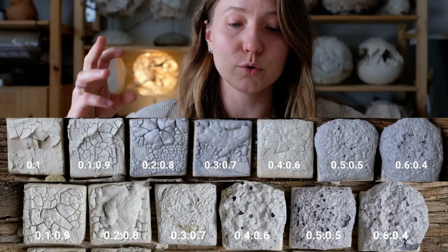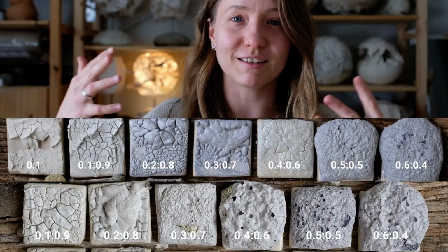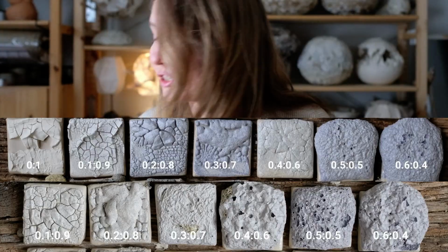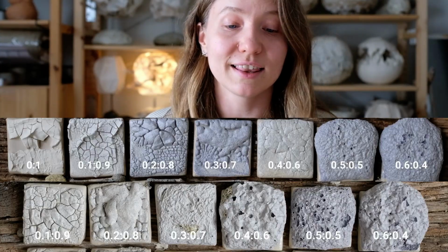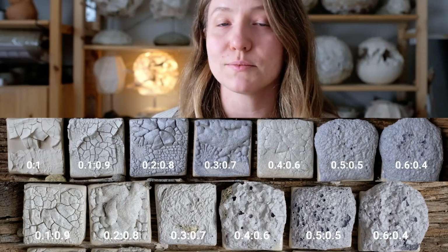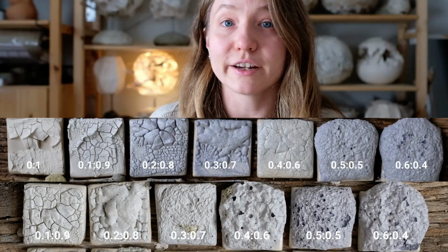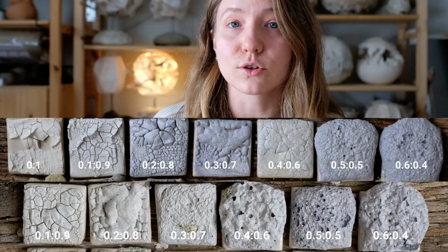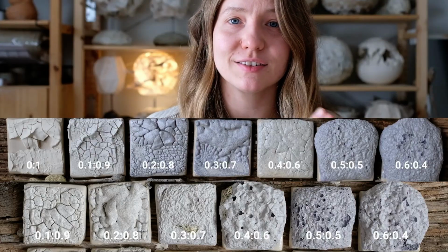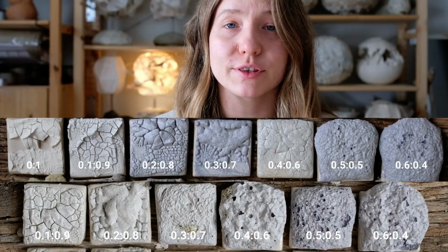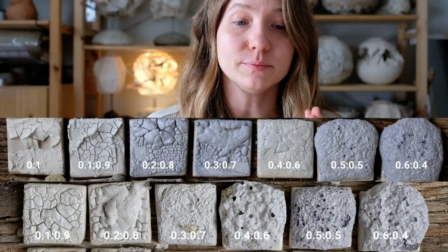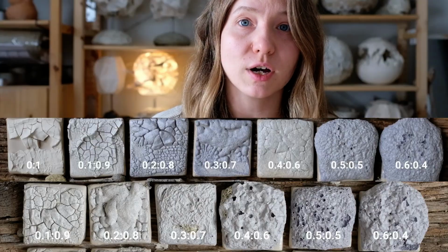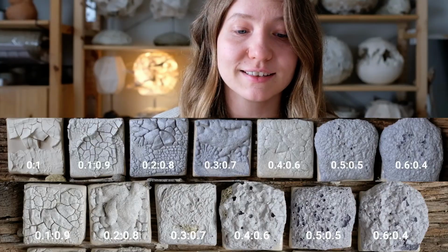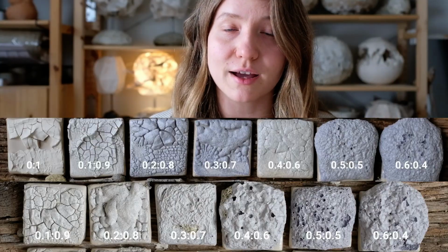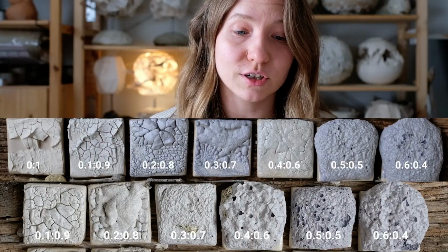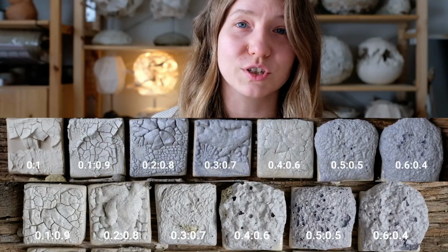So you see, as I go to the right, I have puffier and puffier glaze, versus if I go more to the left, the glaze is less puffy, and sometimes silicon carbide didn't even react at all, and the glaze is also wider. So if we start at 0 to 1 or 0.1 to 0.9 flux ratio, RO fluxes on their own are not enough to melt the glaze, and as you can see, the top left test tile, which is 0 to 1, isn't melted at all, which is why it's cracked.